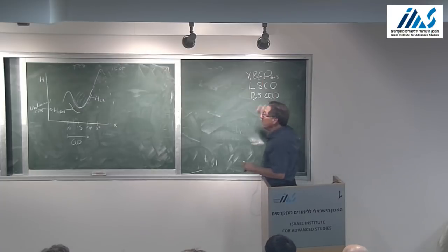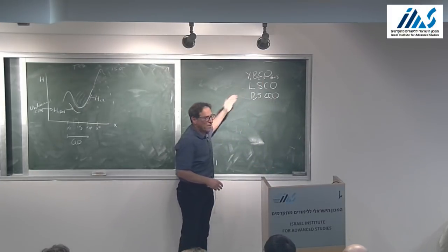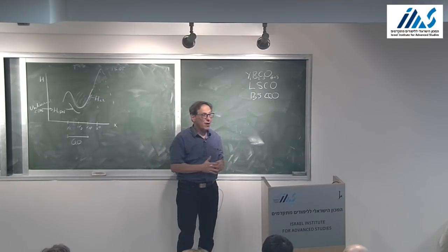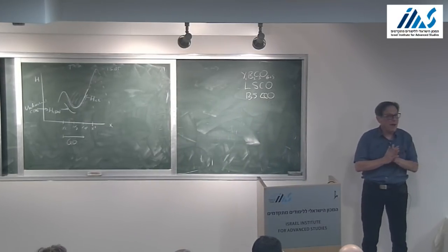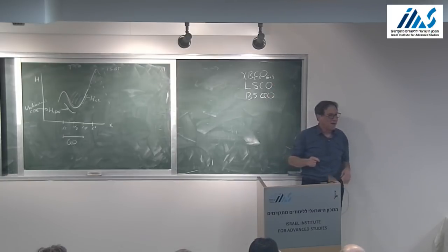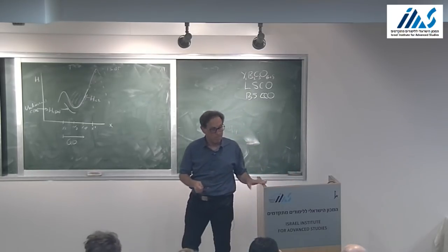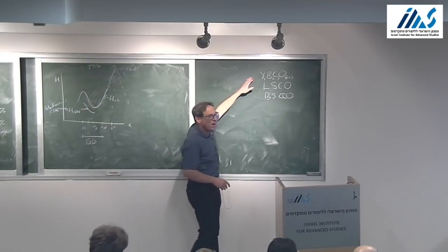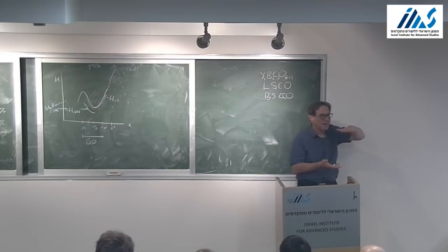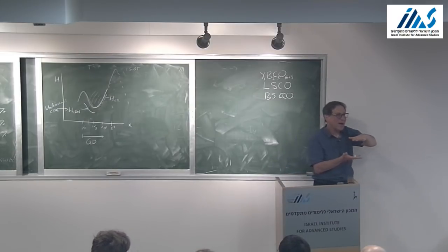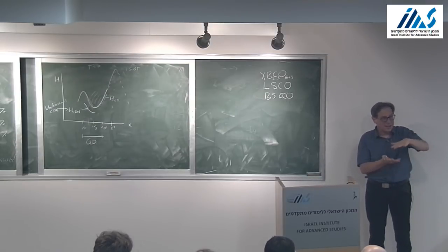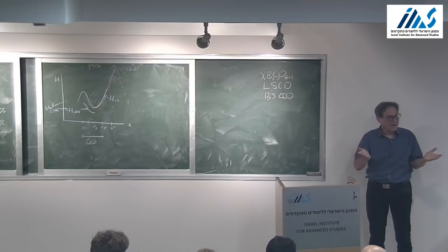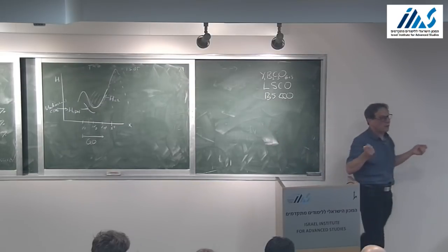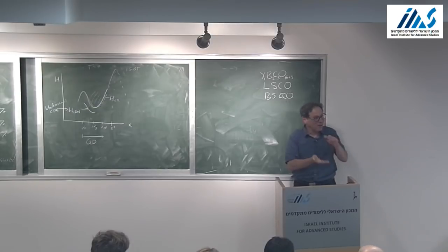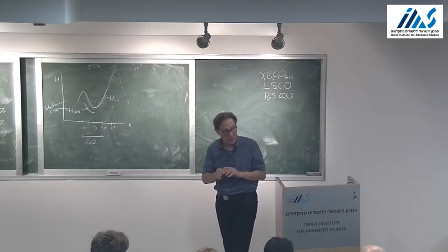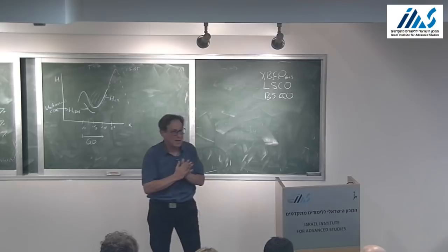So you really have no a priori way of knowing exactly what the hole concentration is in the copper oxide planes. So the way you figure out what the doping is in YBCO or BISCO is you measure something, and for some reason that I don't understand, what people tend to measure is the thermopower at high temperature, and you compare it to what you see in LSCO. And if it looks the same, you say those are at the same doping concentration. Okay? There are some slightly better ways of doing things. As you dope the copper oxide plane, the apical oxygens, which are negatively charged, are electrostatically attracted to it. So it's a reasonable supposition that the distance to the apical oxygen is a linear function of the doping. And so if you have two doping concentrations you know, which you probably don't, but you can at least guess, then under the assumption of a linear deformation, you can use that to measure the hole concentration. But anything you do involves some sort of argument and some sort of hopeful thinking.